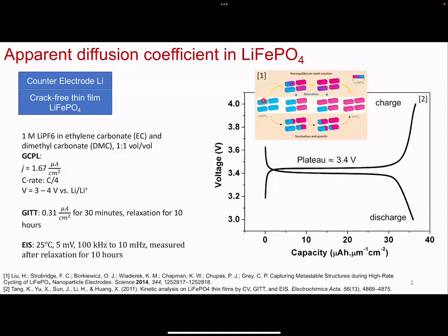But if you try to charge really fast, my comment about lithium iron phosphate having a 2-phase region becomes moot, because then what you could do is bypass nucleation by charging really fast and establish a single phase metastable solid solution. So you're always in a 1-phase regime. You can do that at like 5C, 10C.